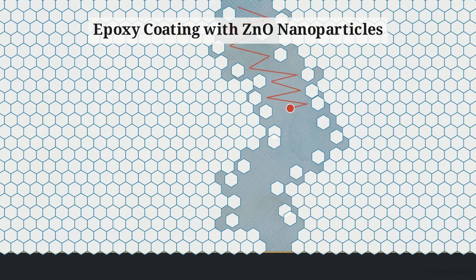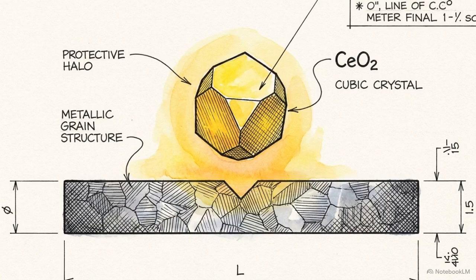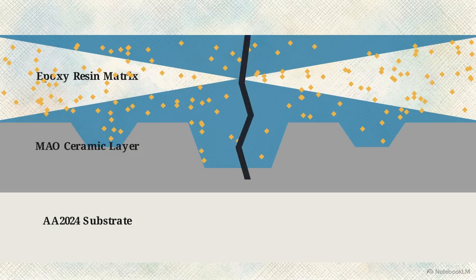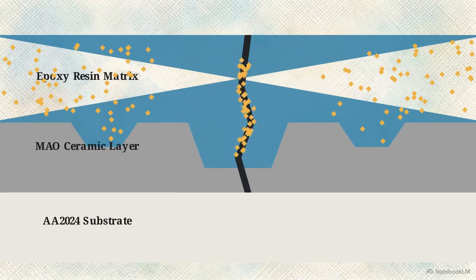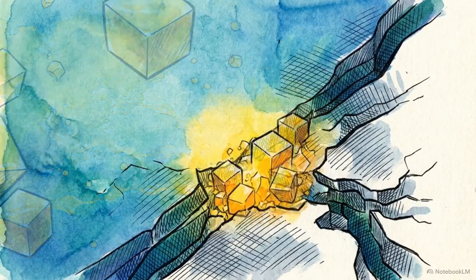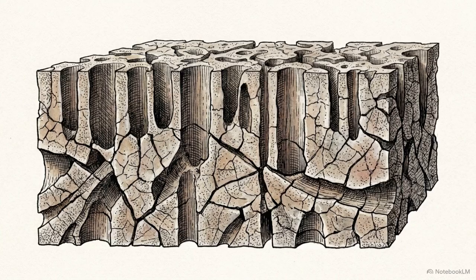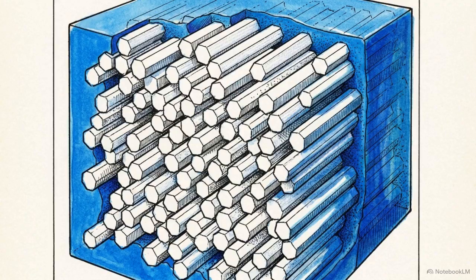While this slows down diffusion, it cannot replicate the active healing properties of chromates if an ion eventually breaches the barrier. This is why cerium oxide is added as a localized chemical inhibitor. When the coating is damaged or aggressive electrolytes penetrate, cerium ions are released and migrate to the site of the defect. These ions form an insoluble passivating layer over the defect, blocking the oxygen reduction reaction and halting corrosion. Every layer has a purpose. The MAO ceramic is the skeleton, the epoxy is the seal. Zinc oxide builds the physical maze. Cerium oxide provides chemical reinforcement.